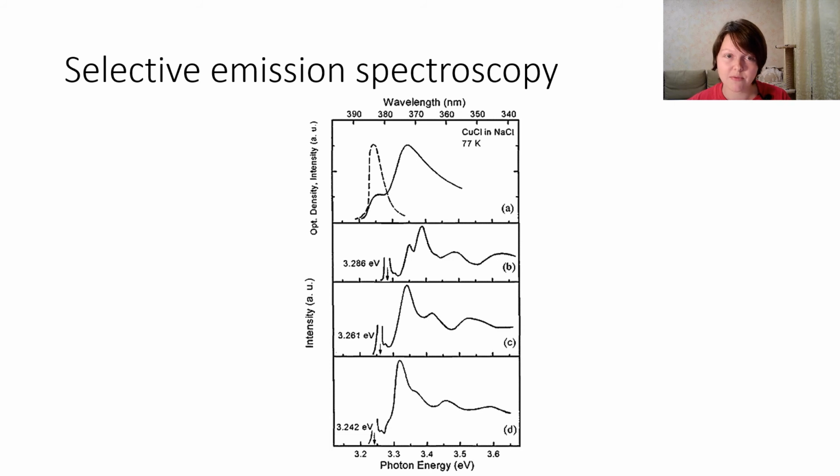So, summarizing this part, we have considered several examples of size-dependent optical absorption spectrum resulting from the quantum confinement effect. In case of the weak confinement range, we can definitely use the effective mass approximation while calculating the experimental results. For smaller crystallites during strong confinement regime, we should also bear in mind not only the effective mass approximation, but the electron-hole Coulomb interaction and the finite potential barrier.